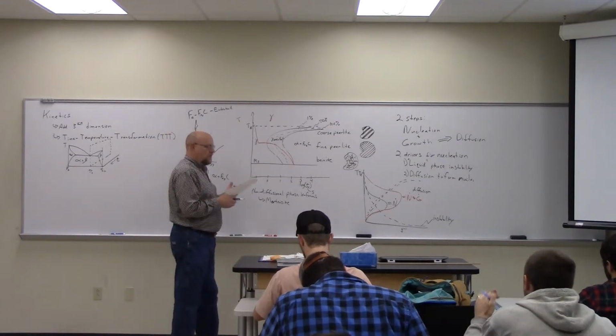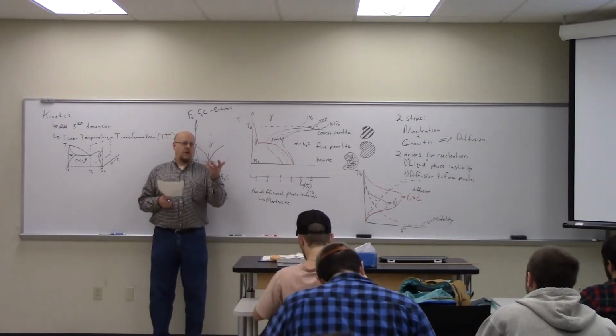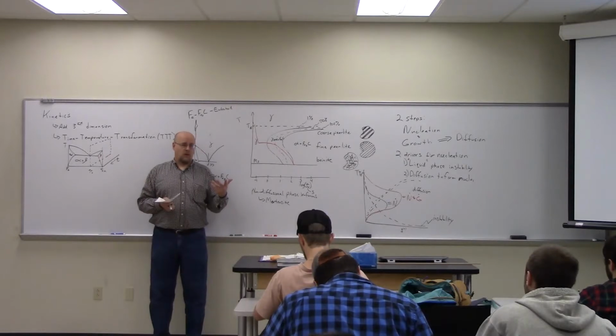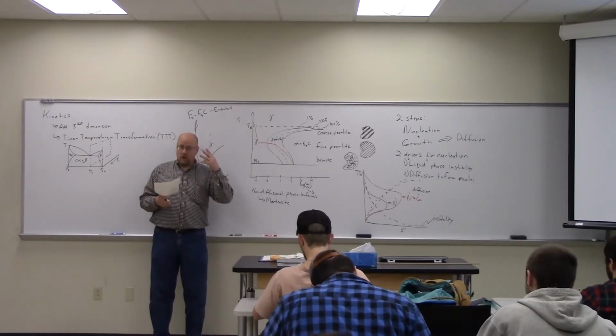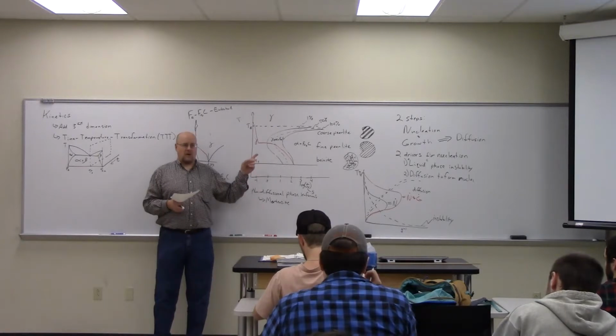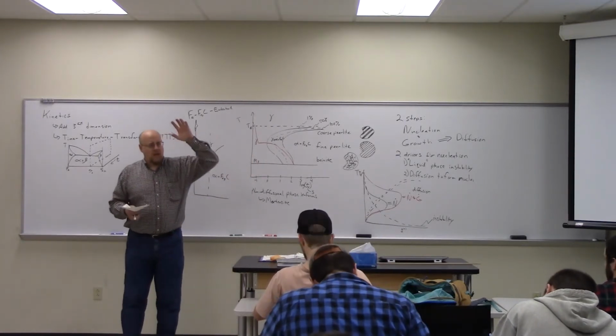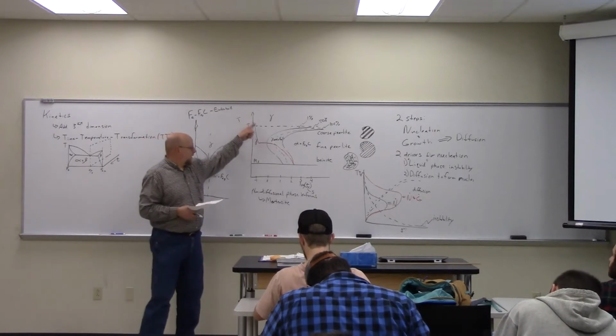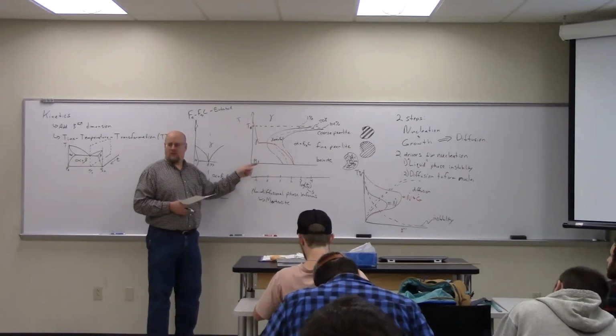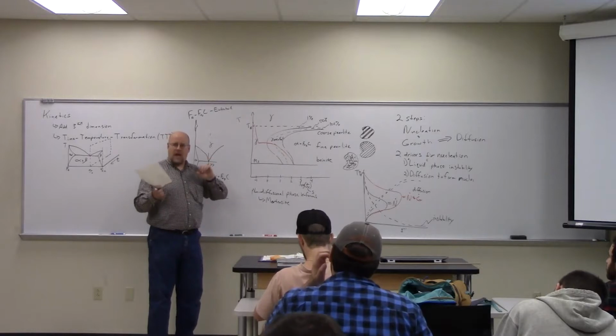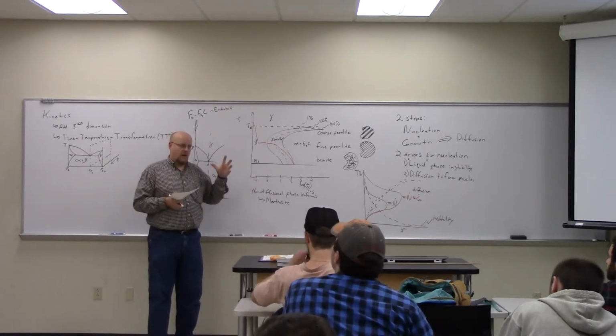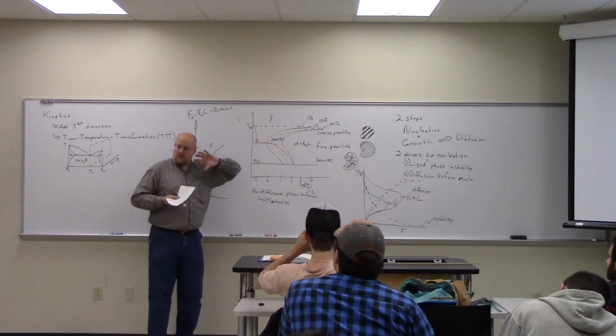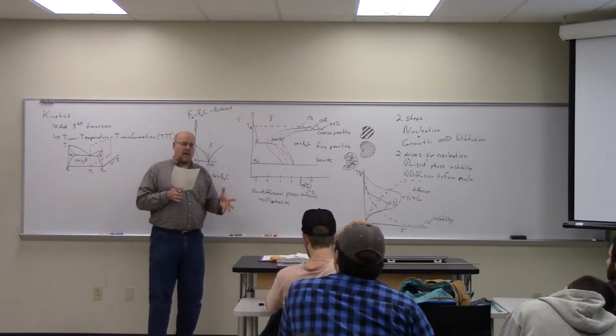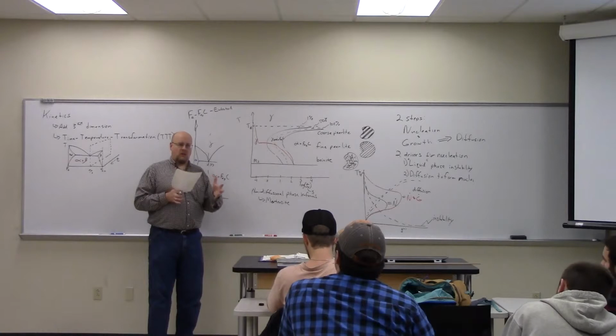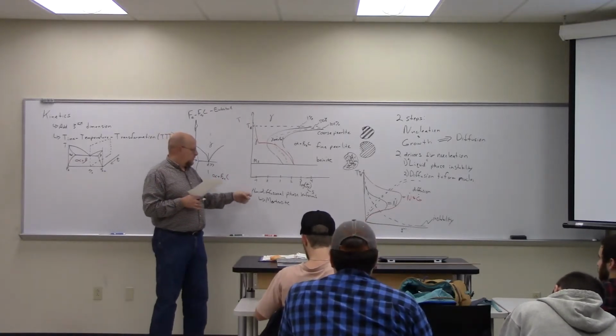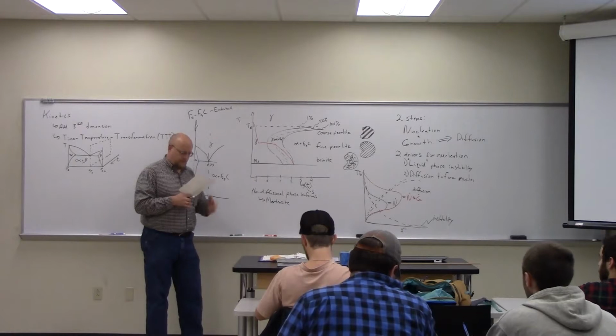It's a sudden reorientation of the crystals. So basically, kind of like twinning. Remember twinning? There was like a ding, right? And you heard it. So here's the same kind of idea. We have these gamma crystals, and we slam them down cold enough. We create such tremendous instability that instead of having to diffuse atoms around to grow crystals of alpha and Fe3C, we spontaneously and suddenly get all of the atoms to rearrange themselves into a different crystal structure, which in this case for steel is martensite.